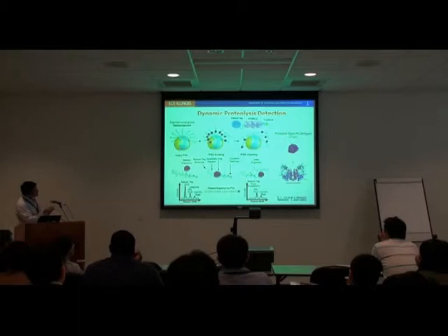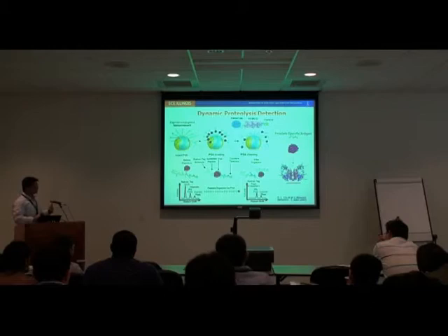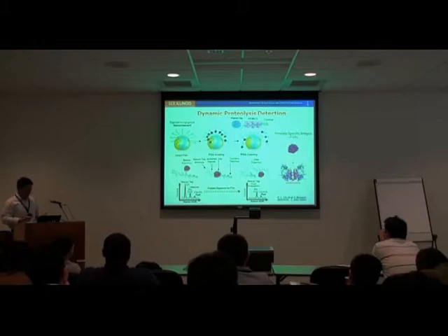And then all the signals coming from this half of the peptides will disappear because they start to detach from the surface, floating away from the surface. And we know that the molecule has to be very, very close to the surface, otherwise we lose the signal. So by using this technique, we can see whether this PSA enzyme, this clinical sample, is biochemically active or not.